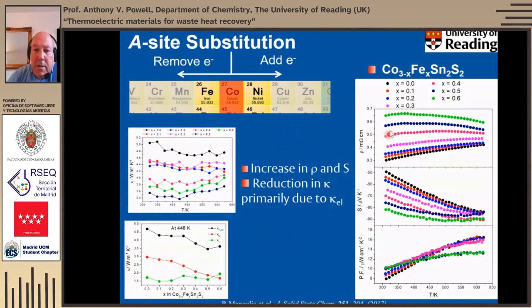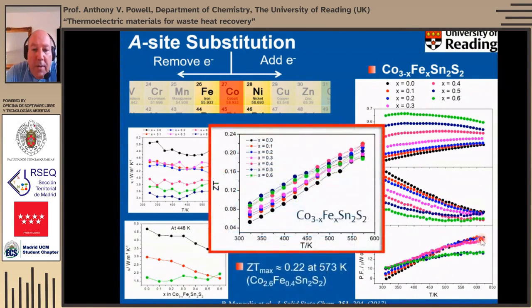So we see this resistivity rises, the Seebeck rises as well, coming down. It becomes more negative in this sense. But the important point is that the increase in the value of the Seebeck outweighs the increase in the resistivity, and consequently we find that we increase our power factor. And therefore, what we find is we actually get ZTs which are slightly improved, maybe not quite as much as they are when we tinker with the B site cation, the tin cation, but nonetheless, we can achieve a similar result by adjusting the electron count through the transition metal cations.